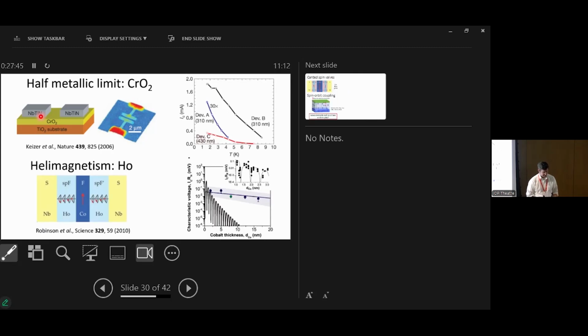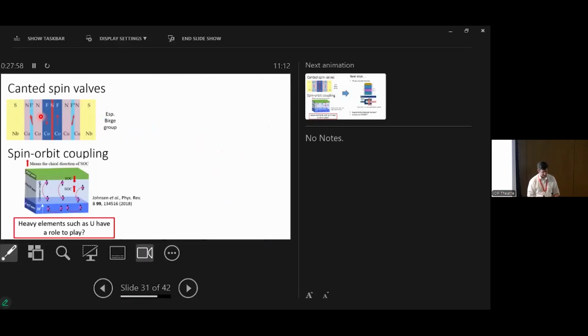The Cambridge group also looked at spiral magnetism. So holmium, elemental holmium, is a helical magnet. So it has a very interesting conical magnetic structure. That's another way of converting singlets to triplets. You can use synthetic multilayers, so layers of cobalt and copper. This is, again, what you would find in your computer roughly as a read head in your hard drive. So Norman Birge's group in the US did a huge amount of work using the non-collinear magnetism here, again, to generate an entirely new type of superconductor.